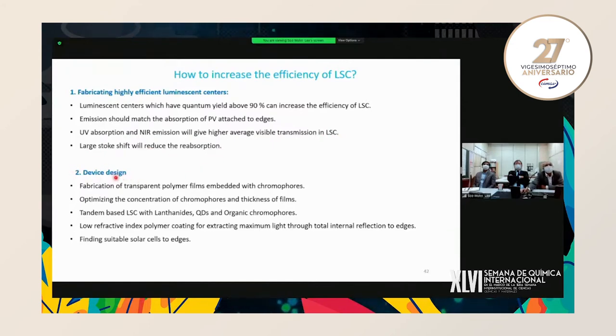And another is device design. Fabrication of transparent polymer film embedded with chromophores, and optimizing the concentration of chromophores and thickness of films to get transparency in the LSCs. And tandem-based LSCs with lanthanides, quantum dots, and organic chromophores to increase the efficiency. A low refractive index polymer coating for extracting maximum light through total internal reflection to edges. And also, we have to find the suitable solar cells for the edges.